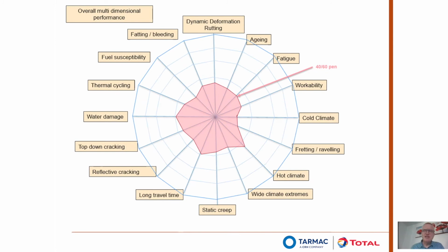So we've looked at a few different areas there of performance, and I think we can summarize that, if you like, on a radar graph. And you can see this is the bitumen contribution towards asphalt performance in all different manners. So it's the holistic performance, if you like, of the asphalt. If we then compare the 40/60 pen against an X70 bitumen, you can see that you're starting to get slight improvement in terms of resistance to fretting and raveling, for example, around this area. You're getting an improvement in performance there. You're getting a slight improvement in areas of reflective cracking. But static creep, because 50 pen is stiffer than an X70, it's a worse performance.